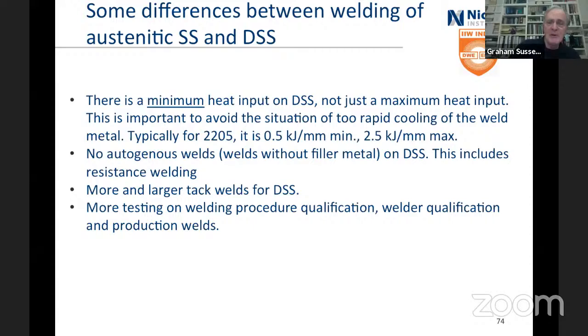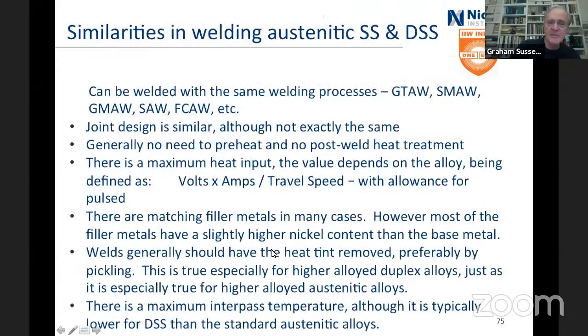There is a minimum heat input for the duplex stainless steels, not just a maximum, and that's so that you don't wind up with nitrides. Typically, it's about 0.5 kilojoules per millimetre minimum and 2.5 kilojoules per millimetre max, in that range. No autogenous welds, I've said that already. Bigger and larger tack welds for the duplex because it's stronger, and more testing, test and test.